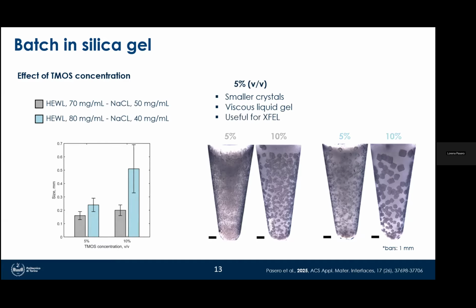And also, this looked like a sort of poorly viscous gel, which may be useful for XFEL applications, but not for our application in this study. And also some parts of the gel appear to be collapsed, especially at the top of the vials. Instead, at 10% TMOS, we observed larger crystals, and also the gelation was complete, and this led to a gel which was stiffer, which formed within 1 day, and this allowed for nucleation to be subsequent to gelation, which is a good property. And this content, let's say, of TMOS appeared to be better for growing crystals in batch for our application.